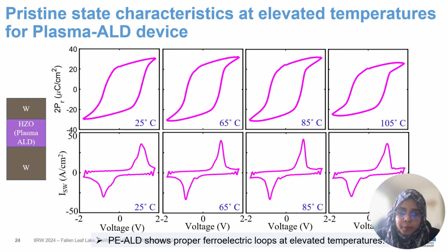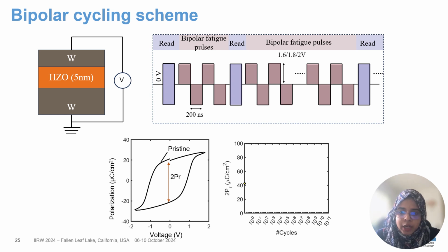Now, since thermal ALD has a wake-up issue, we have to cycle it for getting proper ferroelectric behavior and for waking it up. And this is the bipolar pulse scheme that we have used for waking up our devices, and also to study the endurance. So what we are doing is applying 200 nanosecond bipolar cycles, and we have applied pulses of different amplitudes from 1.6 to 2 volts.